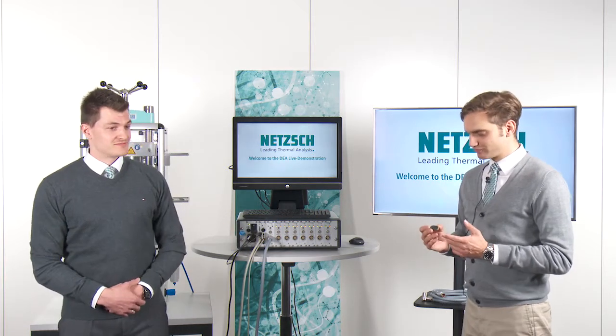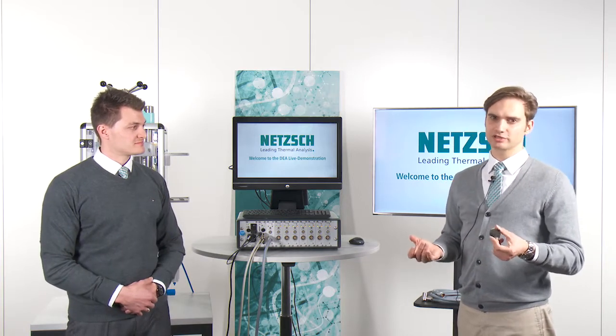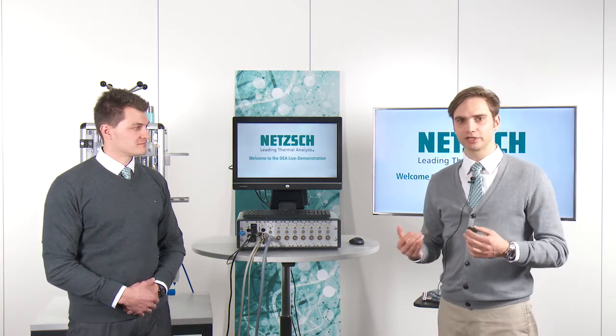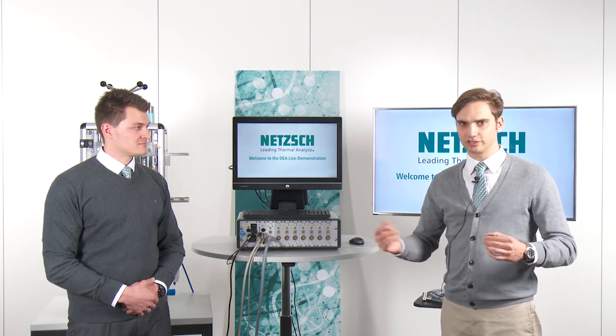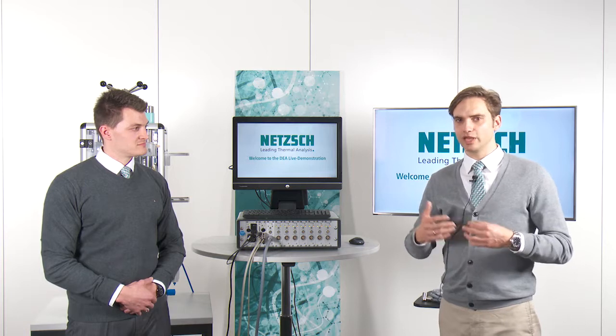Okay, that's a good point. The first thing, we could look at rheology. So we could put this inside a rheometer, and this is very commonly done, that people look at the development of the viscosity of such a resin, and you could see the start of the curing. Yeah. However, it is not so easy to look at the end of the cure.